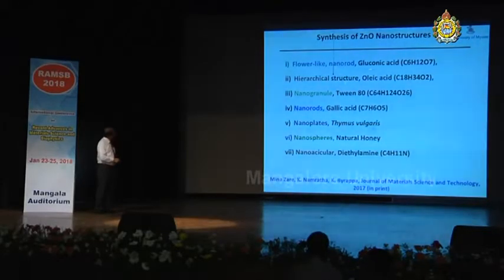Well, I have listed here some of the surfactants we have used and the morphology obtained accordingly. When gluconic acid was used, we obtained flower-like nanorods, and when oleic acid was used, we obtained some hierarchical structures. Tween 80, when it was used, we got nanogranules. Gallic acid gave nanorods. Thymus vulgaris gave nanoplates. And even when honey was used, we got some nanospheres of zinc oxide. And when diethylamine was used, we got some nanoneedles or nanorods.